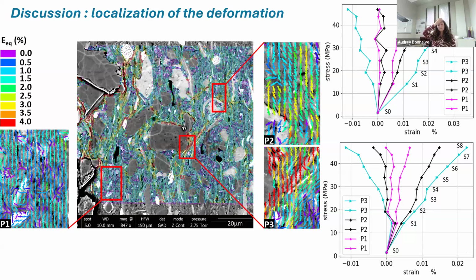Doing those experiments is very nice, of course. Otherwise, we wouldn't be doing it. And it's really cool because it gives you an insight into what mechanisms are taking place and where they are taking place. The idea behind that was to try to understand where in the rock they would take place. So we decided to take different subsets in the image in order to see whether there could be some zones in which you could have some preferential localization of deformation. So we chose 3 different zones.